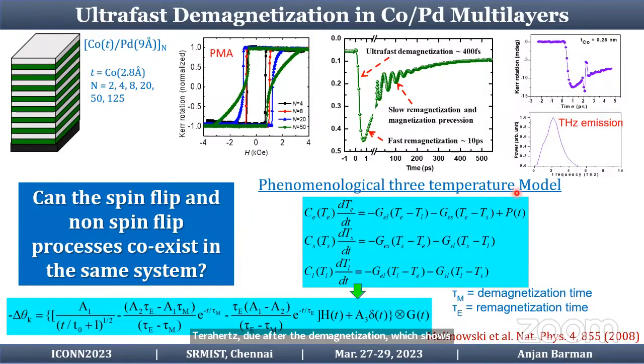So this is the phenomenological 3-temperature model, like I said. These are 3 coupled rate equations with the electron, lattice and spin temperatures and their coupling constants. They can give rise to an expression for the ultrafast demagnetization of the system, which is given like that. Here tau m is the ultrafast demagnetization time, tau e is the relaxation time, and we try to understand what happens as we vary the number of bilayer repeats from 2 to 125.